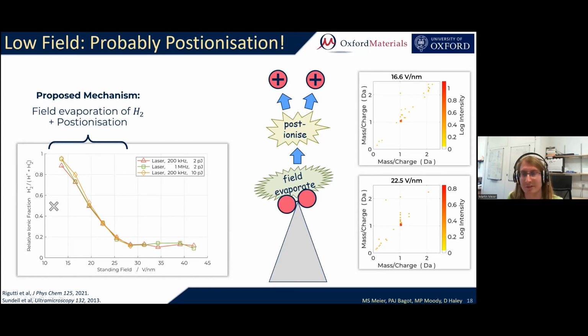16.6 and 22.5 volts per nanometer. And indeed, we see there are quite strong 1-1 events. So H plus followed by another H plus within the same laser pulse. There are way less 1-2 events or 2-2 events in there. And thirdly, there are also other authors who have written similar things or who have done different experiments and come to compatible conclusions. There are 2 references on the bottom left, and there is more in the literature.